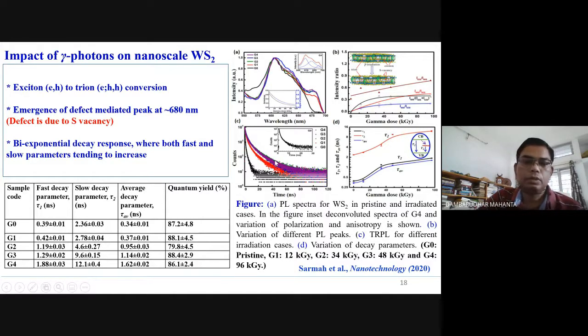And then we have considered TRPL measurements, which is called time resolved photoluminescence, done at UGC DAE Consortium, Kolkata. So there we found that in case of unirradiated sample, the emission intensity quenches very fast, but after incorporation of defects, after incorporation of trions or conversion of excitons to trions, they are now delayed. It means going towards phosphorescence behavior, not phosphorescence, because it is still in nanosecond region. Unless we go to millisecond to seconds or so, we cannot say phosphorescent, but it is delayed emission, you can say.